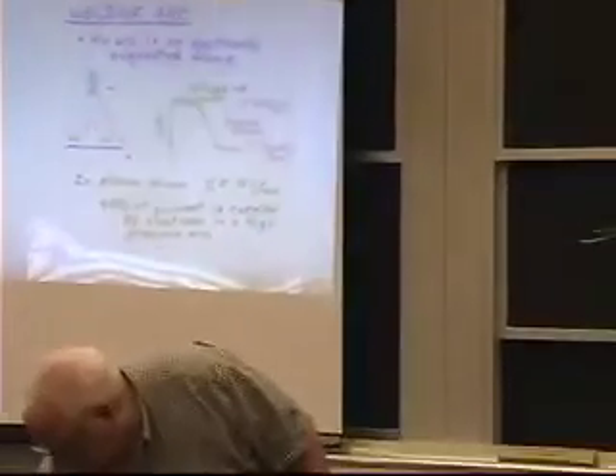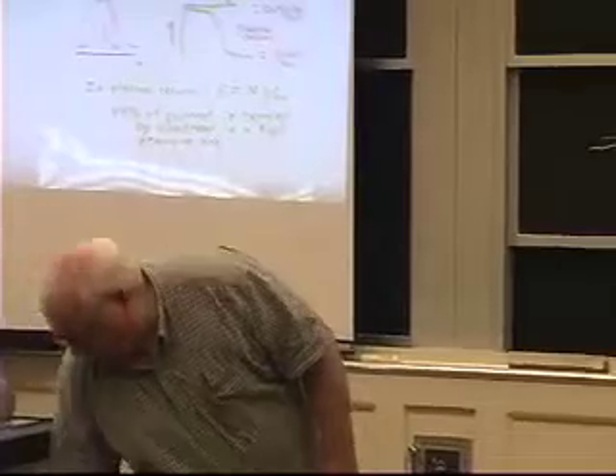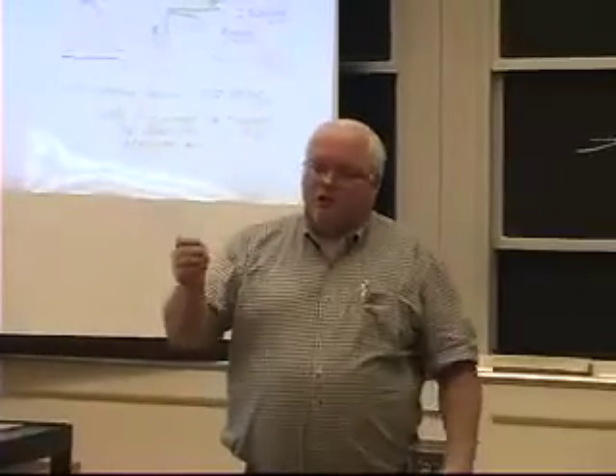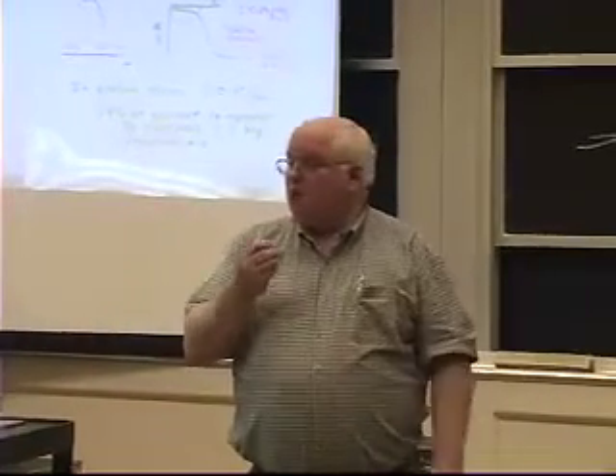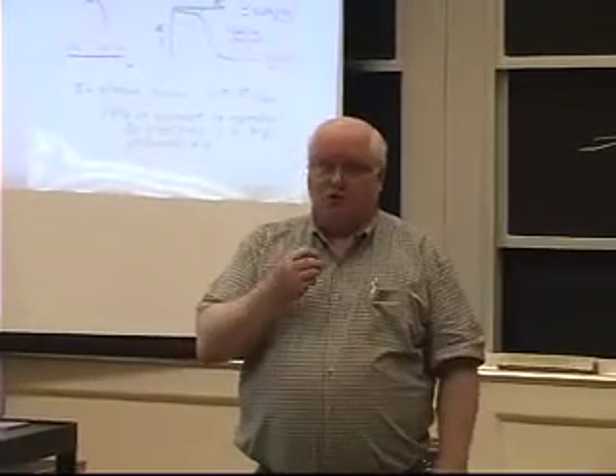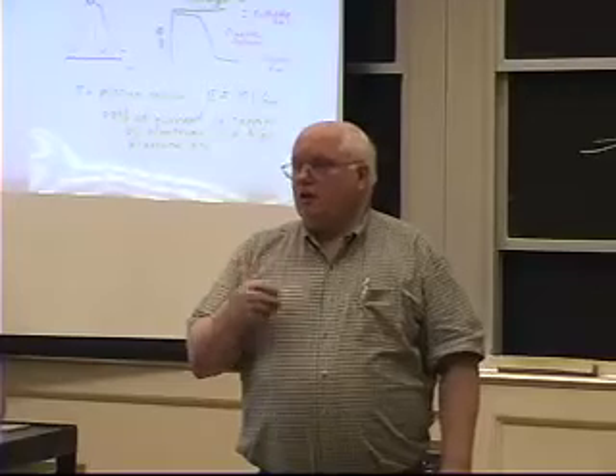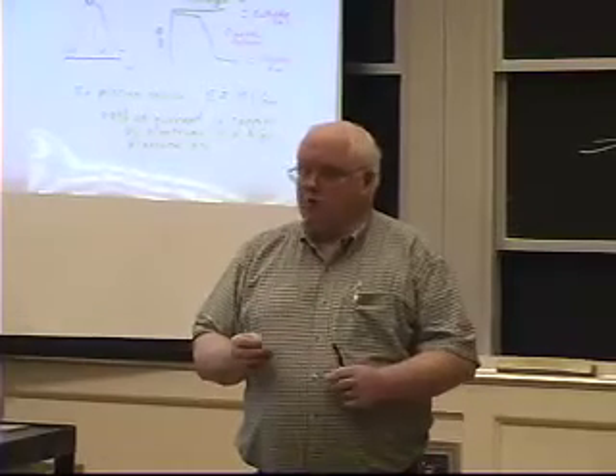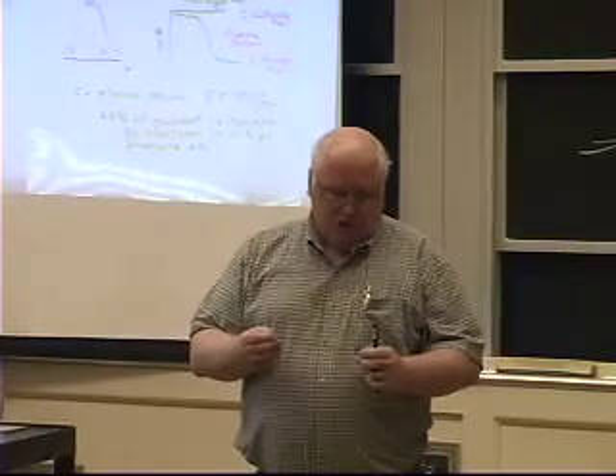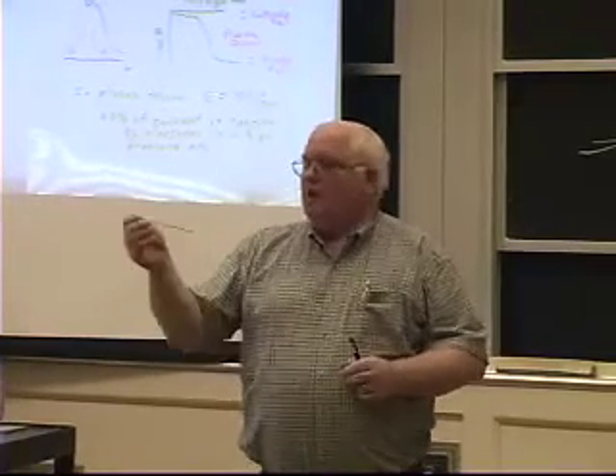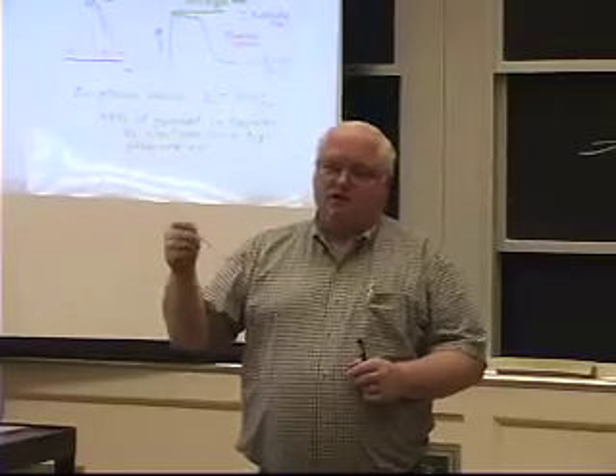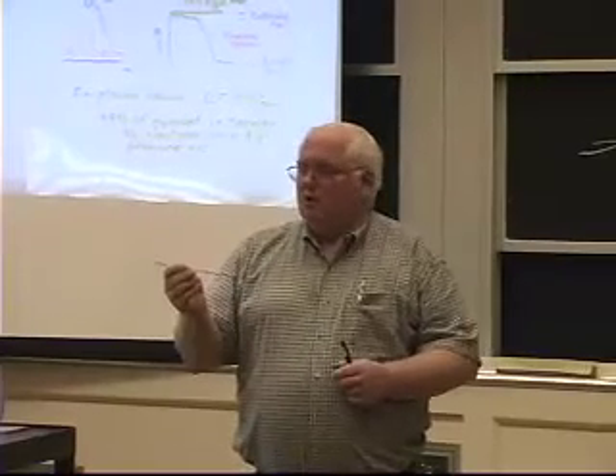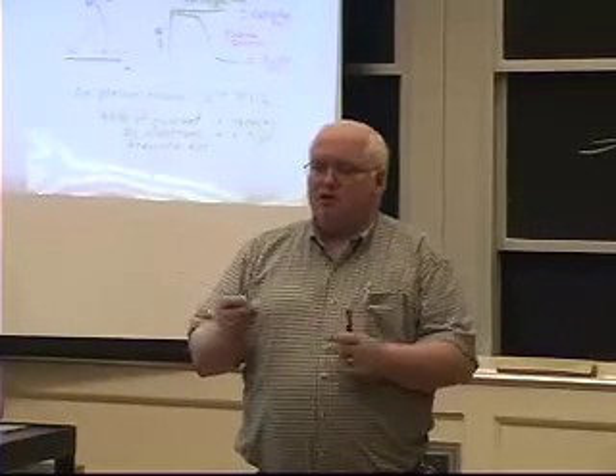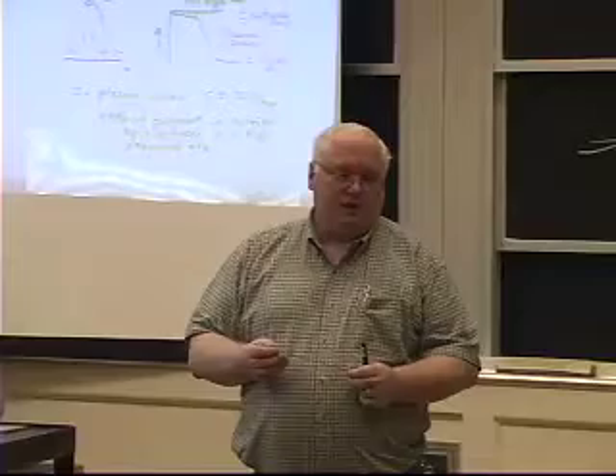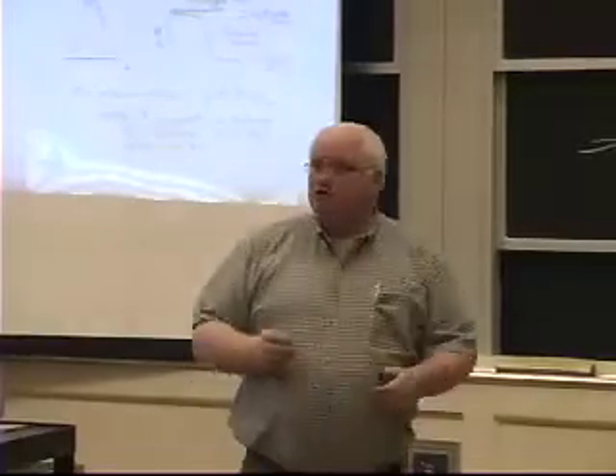It's just a steel rod, like this, and they would melt it off, and it melted just fine. By the way, Sir Humphrey Davy, within one or two years of discovering the electric arc, used it to try to weld, and he did some welding before 1810, but nothing commercial. But when they tried to weld steel, the most common material, you ended up with Swiss cheese for your weld. The problem gets back to nitrogen in the air.